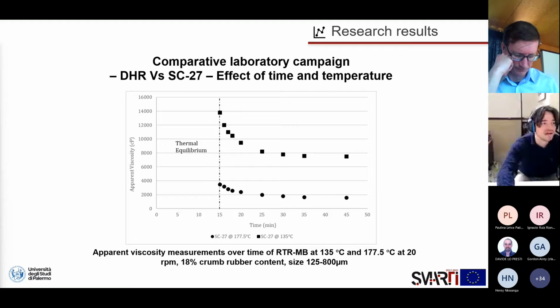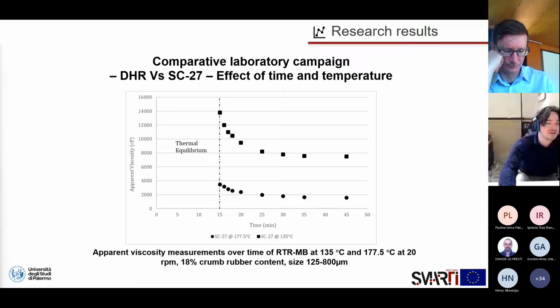Here we can see a picture that shows the viscosity reading of crumb rubber modified bituminous binder at two different temperatures using a standard cup and bob spindle. According to the standard, for the first 15 minutes the viscometer motor was off in order to allow the sample to reach thermal equilibrium.